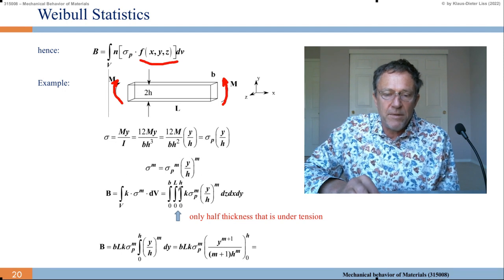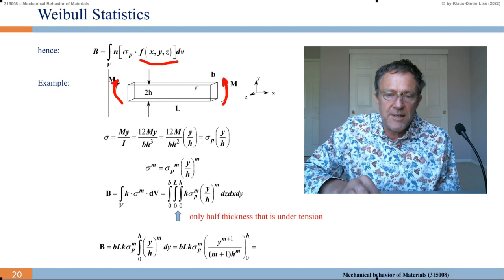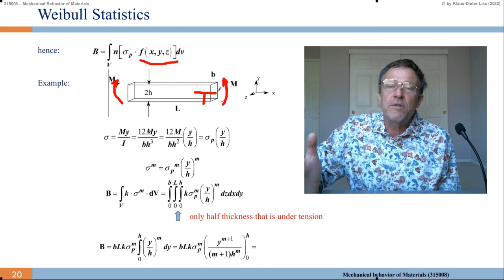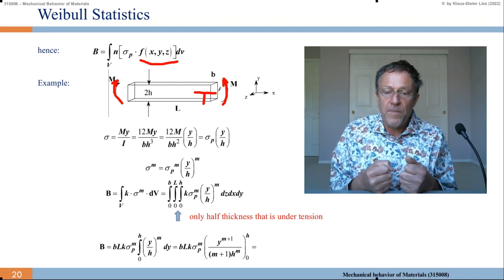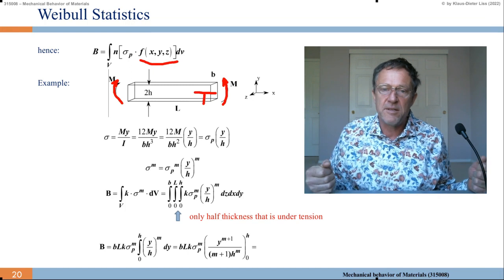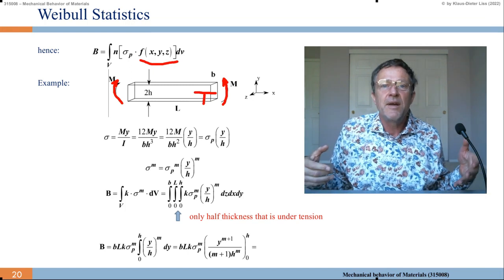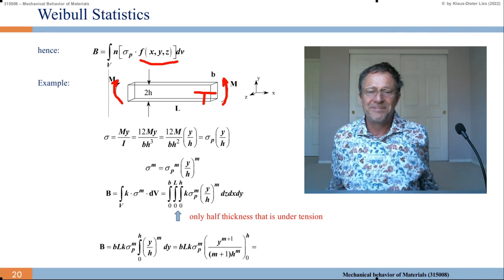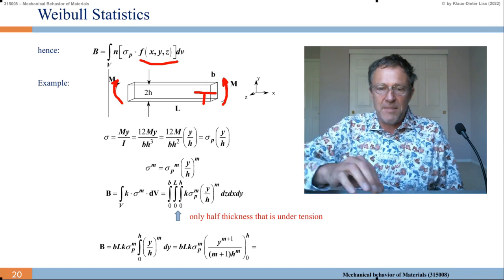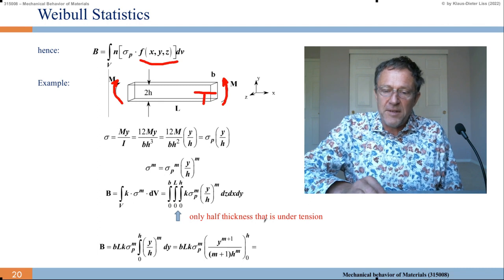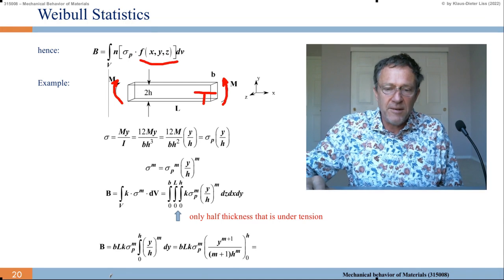And we can integrate that, but we only integrate it over half the thickness. So the thickness from here to the bottom, if this is the tensile region, because in the compressive region we would not have crack initiation, we have closure of cracks. So the material only fails if the crack opens. So this was the sigma critical which I introduced and then put to 0. If I'm smaller than that sigma critical, then nothing happens. The cracks would close in this way. So we integrate only half the thickness, namely that one which is under tension, and get this formula here. It looks a little bit complicated. Now you're better at mathematics than I, so I let you do that.